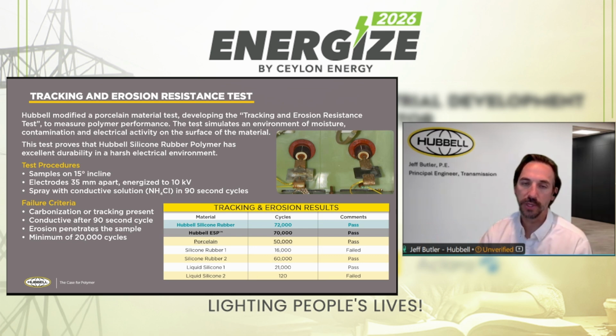As I mentioned at the beginning in the history of Ohio Brass, originally we were manufacturing porcelain insulators, so this was a test that we used to evaluate the integrity of the porcelain samples, and we adapted it for evaluating the integrity of polymer insulators. In that regard, for porcelain we had a minimum threshold of 50,000 cycles.